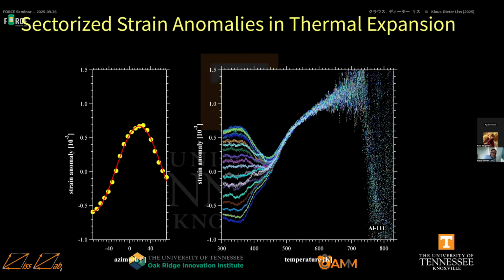And then I can look as a function of orientation. And as a function of orientation, I get this sinusoidal shape. So what I want to say here, and this is the point you need to take, is that we have residual stress as a function of azimuth, the azimuthal angle. The displacement is orientation dependent. That means we have a strain ellipsoid.